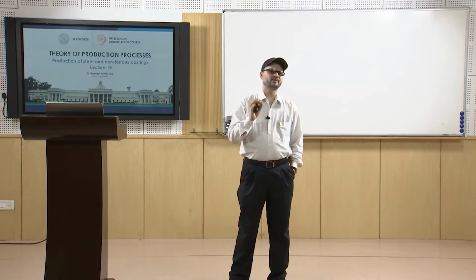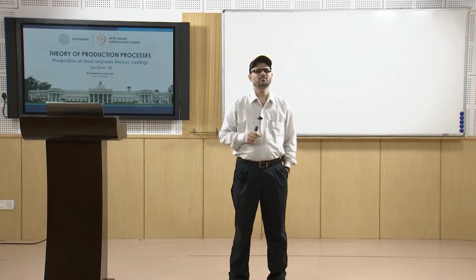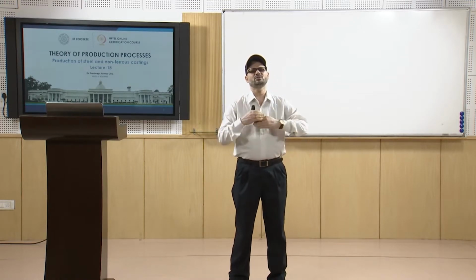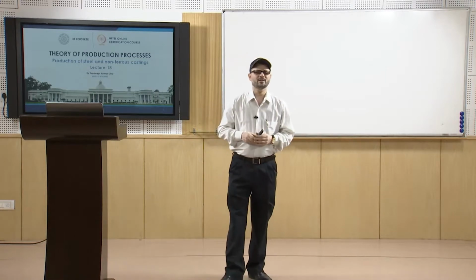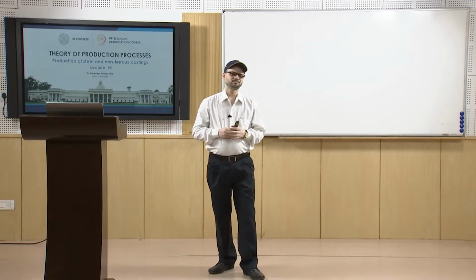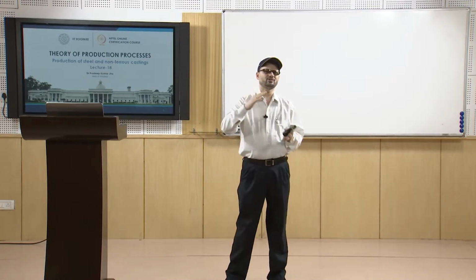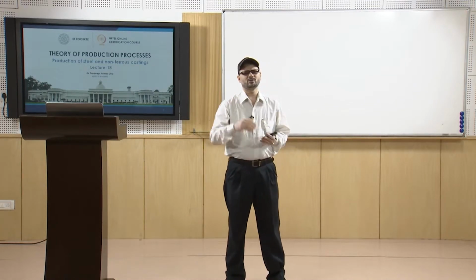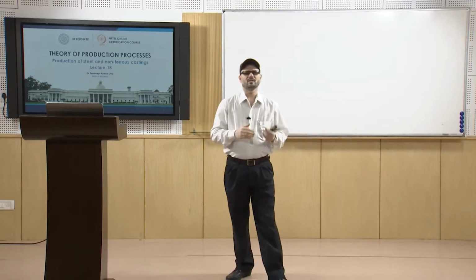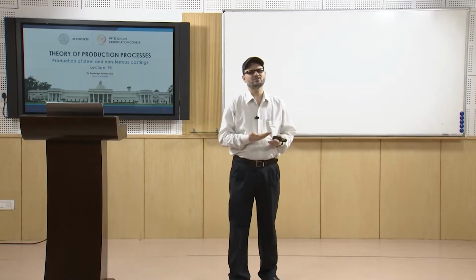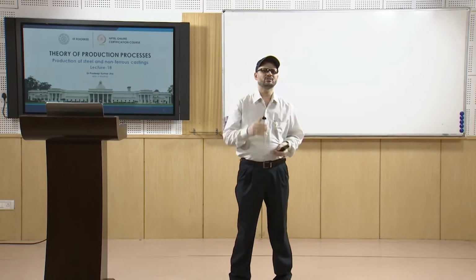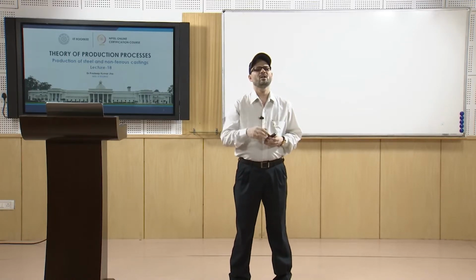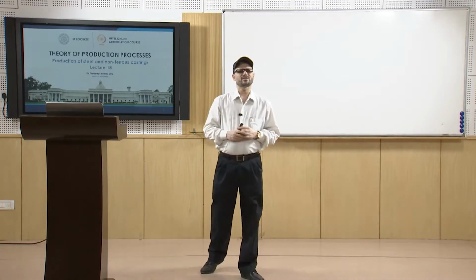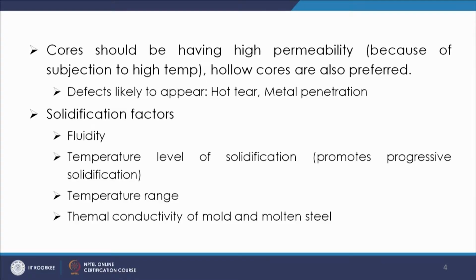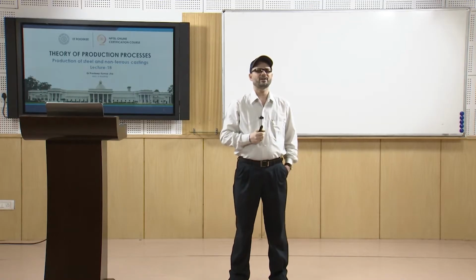Temperature level of solidification. So, that is also important because you need to have the progressive solidification. So, once we give the temperature at higher temperature, and because of the temperature gradient, the molten metal touching the wall will start solidifying and then it will move towards the inner side. So, that will promote the progressive solidification. Temperature range, as we discussed, that is also the freezing range. So, that affects the solidification mechanism.